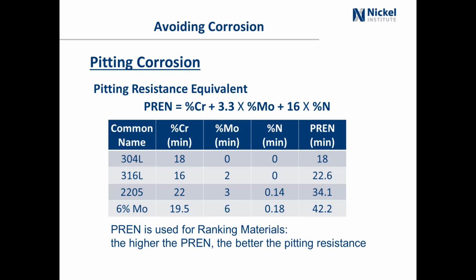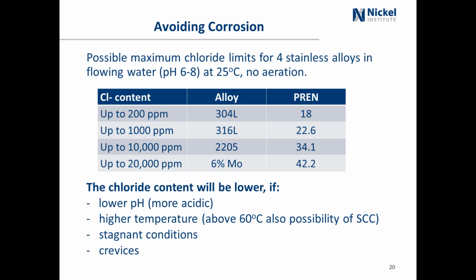PREN is used for ranking materials. The higher the PREN, the better the pitting resistance, but it's just a means of ranking. You can't use it to determine whether a stainless steel is going to be resistant to pitting in a particular chloride environment. Here I'm just showing possible maximum chloride limits for 4 stainless steels in flowing water at about a neutral pH, at 25 degrees C with no aeration.